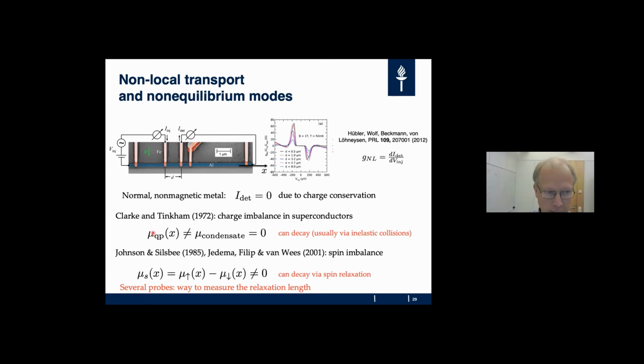Charge imbalance basically means that the quasi-particle potential is different from the condensate potential. And even though there is charge neutrality, such a quasi-particle potential can actually decay because once the quasi-particles are connected with the condensate, they are transferred to Cooper pairs. This decay is usually via inelastic collisions.